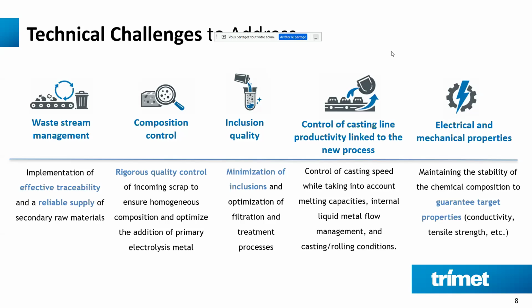And at the end, obviously, because that's something which remains a prerequisite, we cannot mitigate on the electrical and mechanical properties, and we didn't change the specification at all. Meaning that whether we deliver wire rod to the cable makers with or without recycling content, it has exactly the same properties, electrical and mechanical. So there's no mitigation on this, to ensure that at the end the cable has exactly the same properties. So those are the different technical changes we had to go through for this experiment and also over the last years.